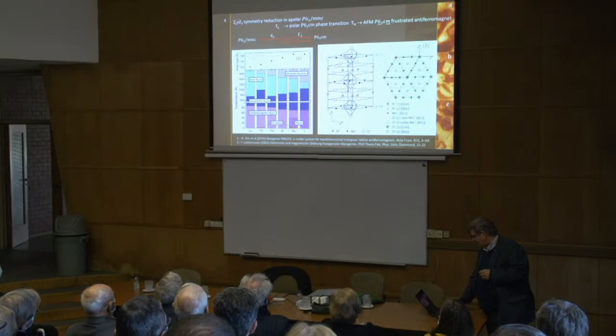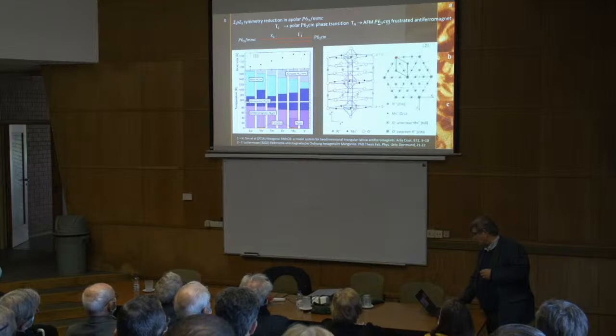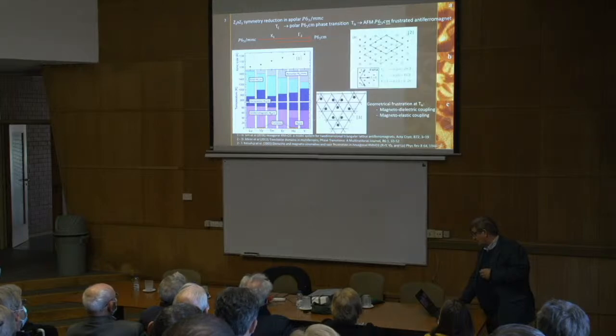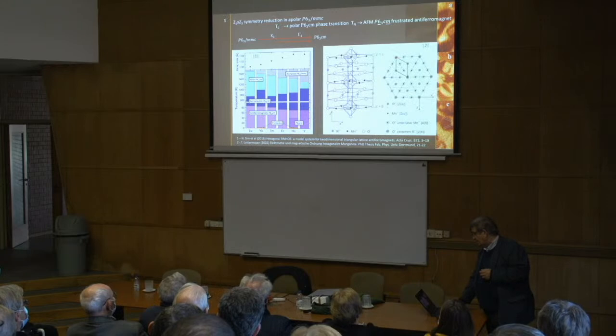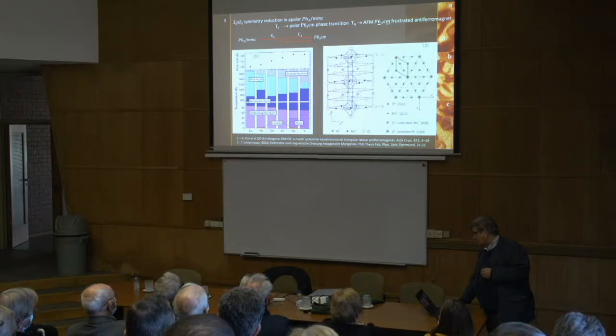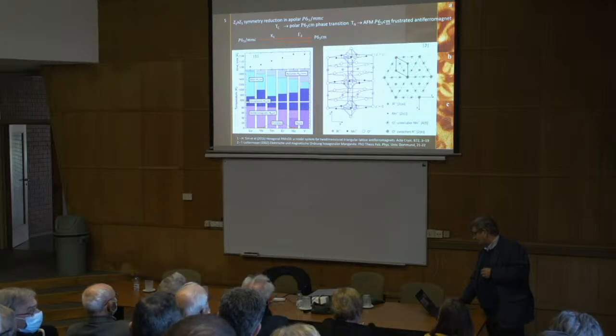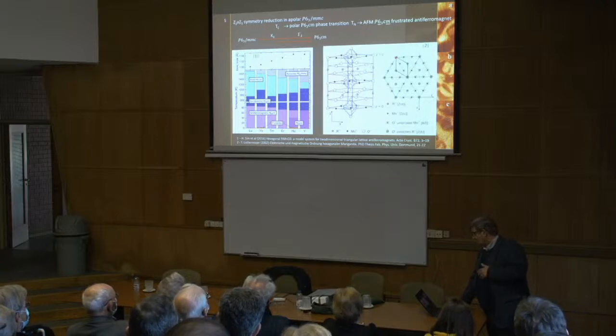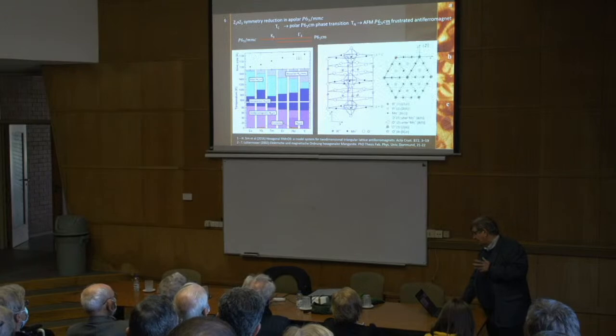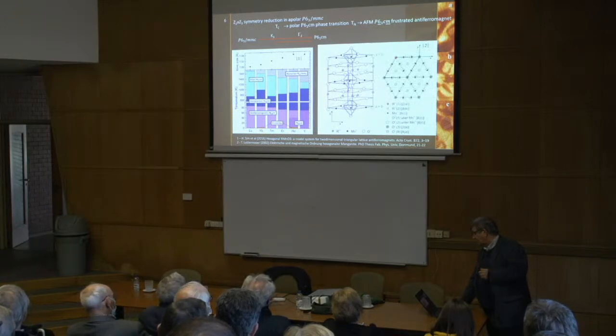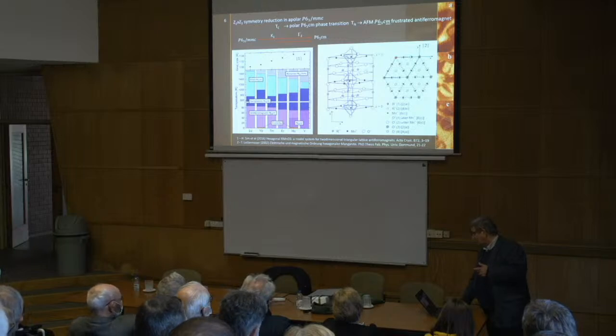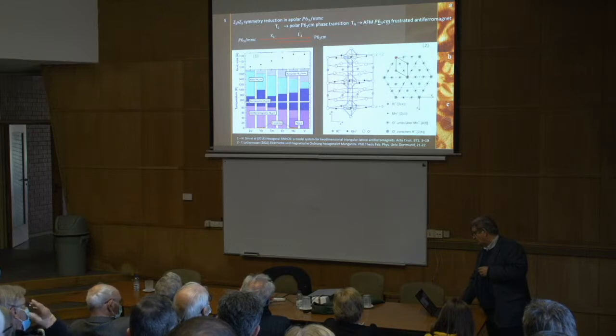The trimerization is really a superlattice, but can be described as a superlattice of the highly symmetric phase. We can see on the left how the atoms are moving. Manganese is not changing much. The rare earth is moving, and there is a polar oxygen that also moves. We may say that the superlattice has much wider lattice sides, but for plasticity, as I will show, we can always express dislocations as true dislocations, not partial dislocations of that lattice. Okay.